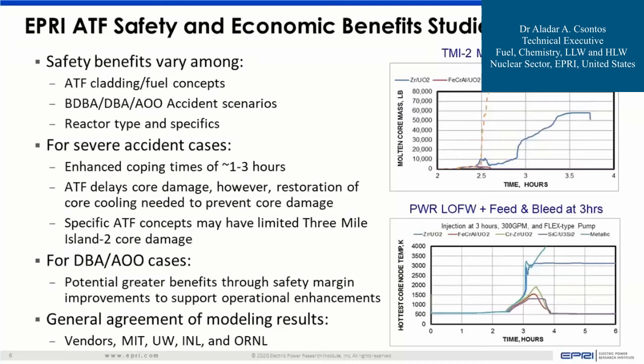And so when we look at specific examples, we did look at a Fukushima case, and we did look at Three Mile Island. And this upper picture here, this graph here, is an indication of the TMI-2 molten core mass as a function of time during the accident, and the different concepts that we had up here for the ATF fuel concepts. And you can see here that this is the Zirc UO2 system, and the coated claddings, the silicon carbide, and the FeCrAl, or IronClad, as it's called, they all have a much lower molten core mass compared to what occurred during the Three Mile Island event. Okay, so you can see here that ATF would have limited the accident core damage at Three Mile Island.